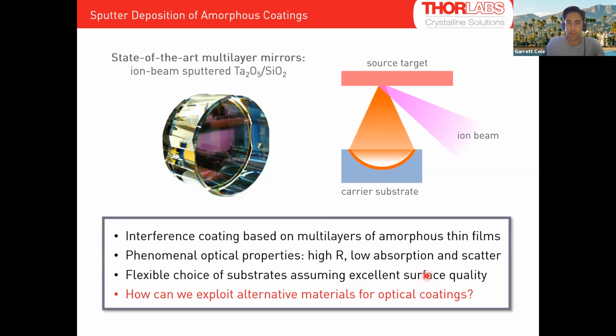So, I'm not an ion beam sputtering expert, but I'll give a quick overview here. State-of-the-art multilayers are typically alternating high-index tantalum pentoxide with low-index silica. And this is usually deposited as shown conceptually here. You have an ionized beam of noble gas atoms impinging on a target. The target could be directly an oxide, or it could be a metallic target in an oxidizing environment. And you effectively sputter atoms off of that surface and have them adhere to your final substrate.